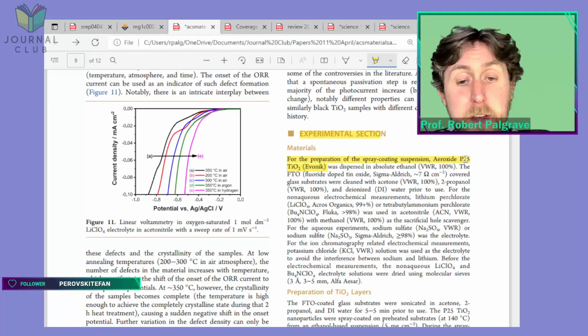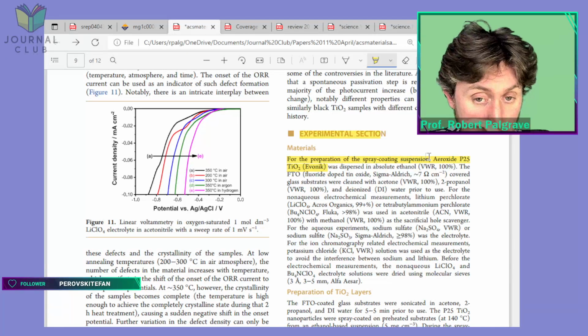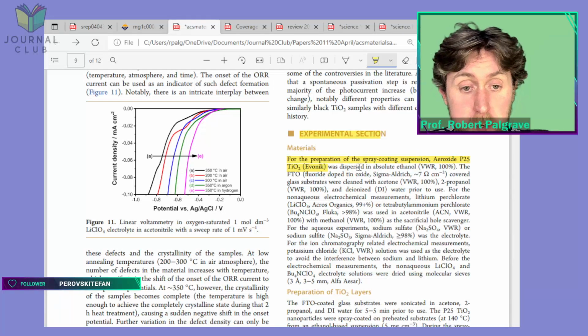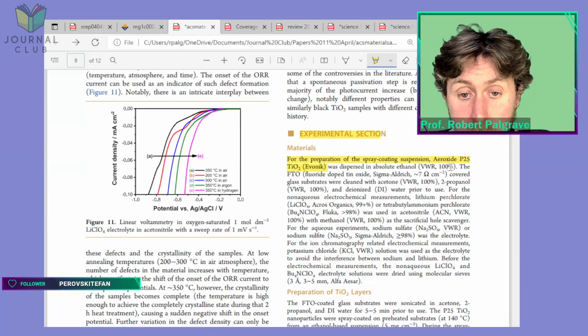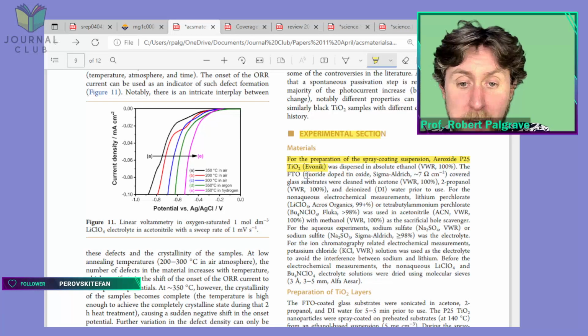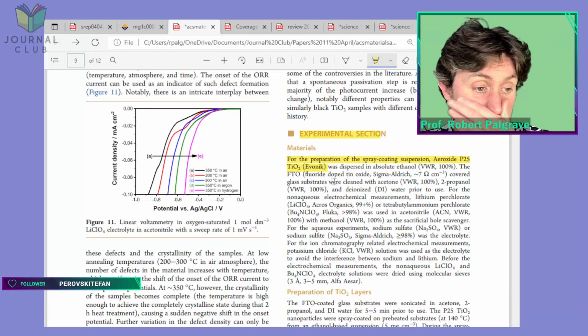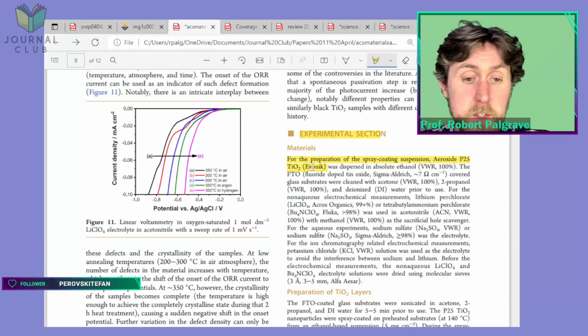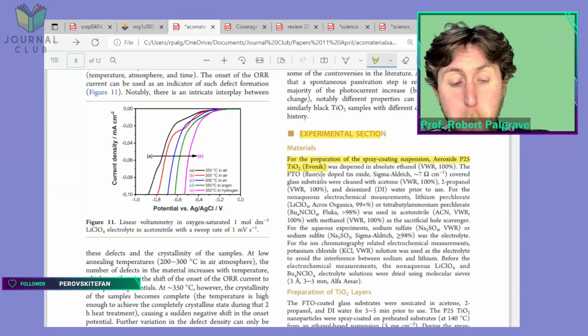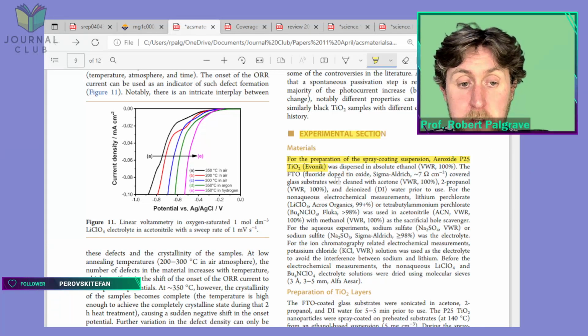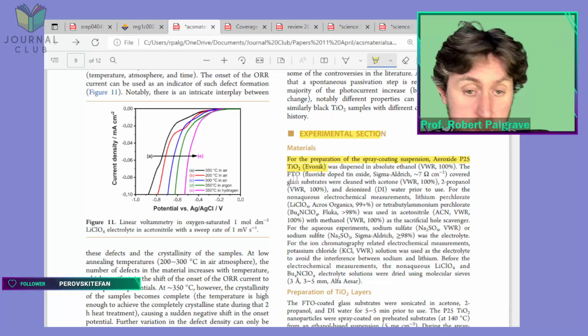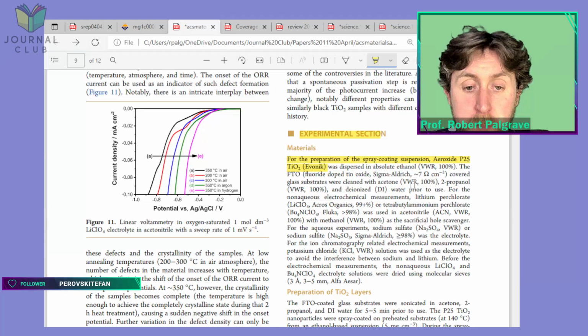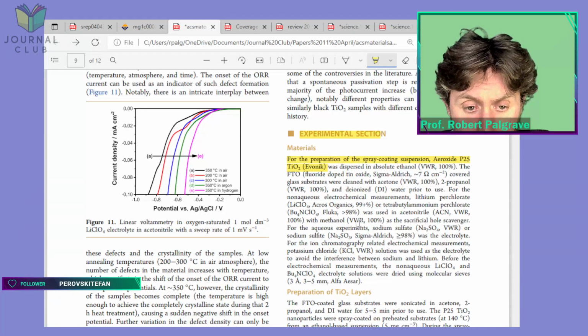Anyway, so they took basically the best undoped photocatalyst you can have. They dispersed it in ethanol. Fair enough. FTO is fluorine doped tin oxide. So they talk about now a layer. So FTO covered glass. This is a conducting layer. They need a conducting layer because they're doing electrochemistry. So they need to deposit their P25 on a conducting layer. So they took some FTO coated glass, so conducting glass basically. They cleaned it a certain way. Blah blah blah.